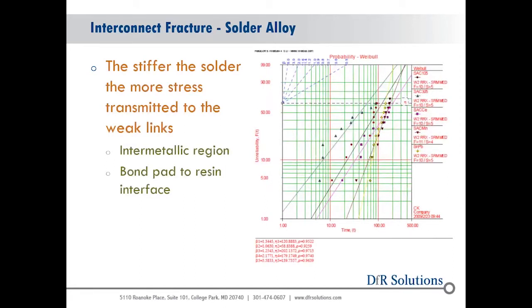Definitely a thing of concern is with lead-free, it is a stiffer solder. It does put more stress on the interconnects. Therefore, its number of drops to failure is typically lower. So this is just a good example of that. You have the yellow line, which is tin lead. And then you have your standard SAC 305 here on the left. So definitely a significant reduction in the drops to failure because of intermetallic fracture and pad cratering. Because the yield stress of SAC is much higher, the solder doesn't deform and absorb the stress.